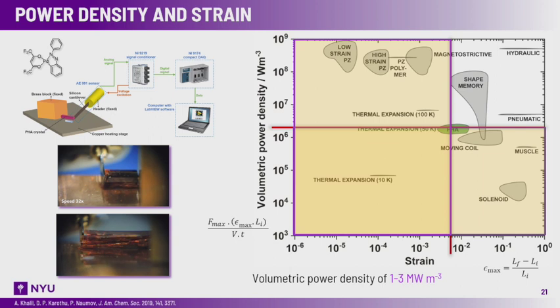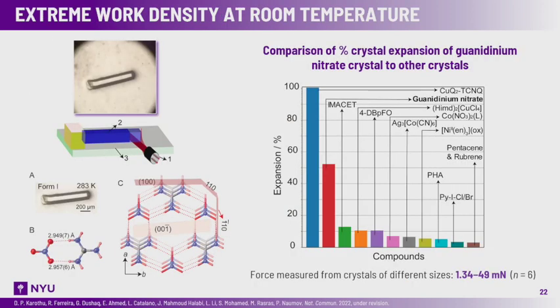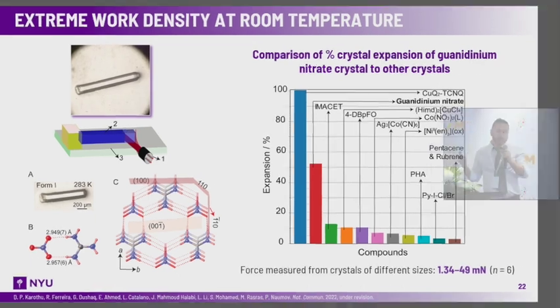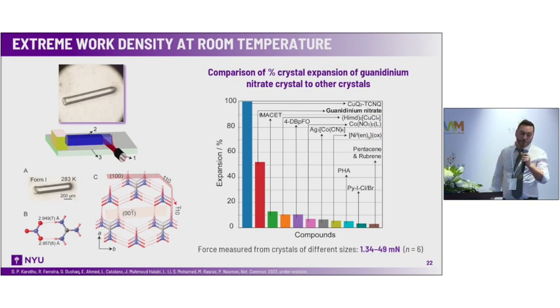Unfortunately, many of them disintegrate throughout the process, so it's not very easy to directly transfer this into applications. But in some cases, we have examples that really retain their integrity over repeated cycles of actuation, and these are the most important for future applications. In this particular case, we discovered a material, the paper is now under review, a simple crystal, guanidinium nitrate, which shows about 50% expansion when you heat it over a phase transition around room temperature. This is a record holder, I would say, in crystal expansion, which translates into a very high work efficiency for this material.